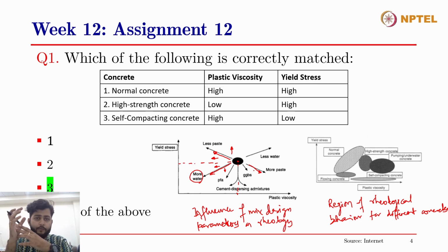So for the concrete to flow through a path, it will require more force, or it will flow at a lower velocity when you pump it through the pipe or the hose. Now when the velocity is low, it means that the viscosity is high in the concrete. So this is how the different mix design parameters affect the rheological behavior of your concrete. Similarly, if you add some mineral additives like fly ash or blast furnace slag, this is how it affects the yield stress and viscosity and so on.